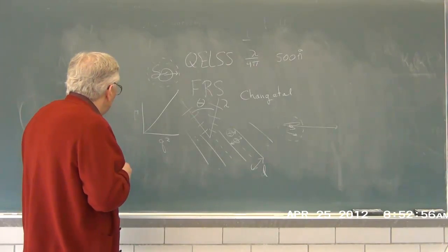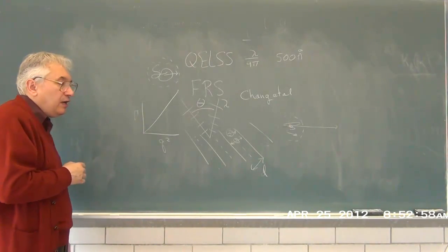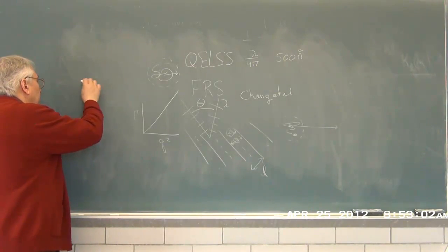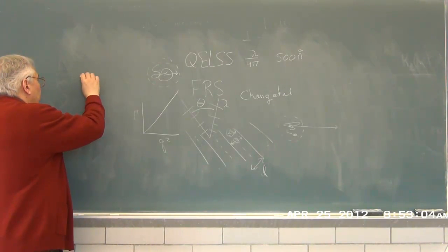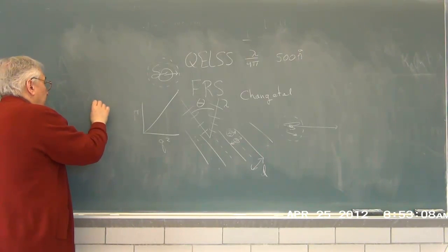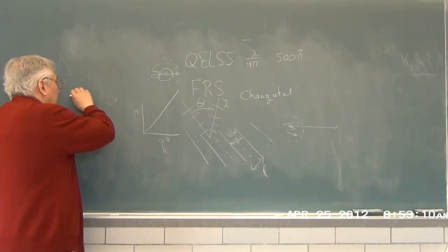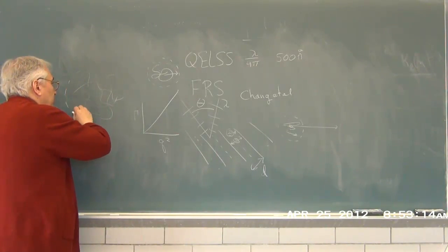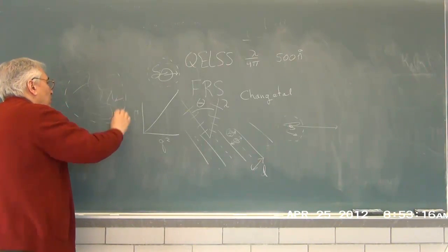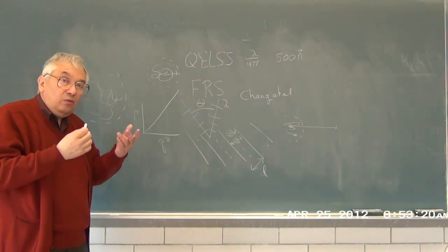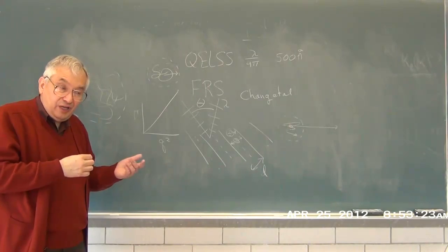More experiments done by Streletsky on hydroxypropyl cellulose came to the conclusion that at higher concentrations you see a third very slow mode, and the very slow mode corresponds to the motion of objects that are quite large. How do we know it corresponds to the motion of objects quite large? Well, we took the same polymer solution, he did.